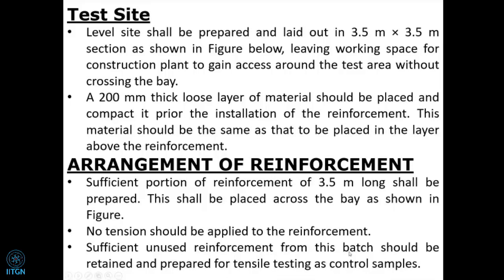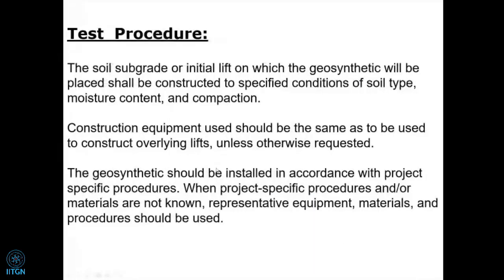After rolling for a particular number of rolls, we have to exhume our samples and test them in the UTM in the laboratory. So what is the loss in strength prior to the installation and after the installation? That ratio gives your installation damage factor, RFID. I will show you how.